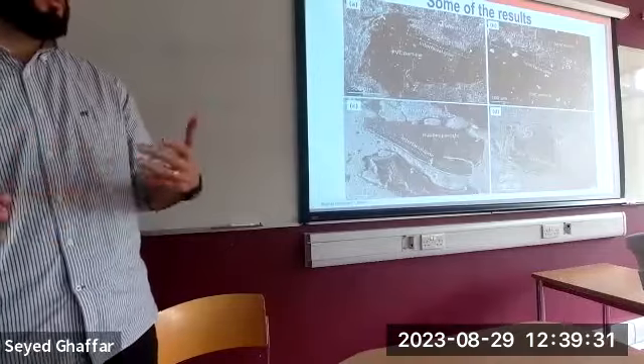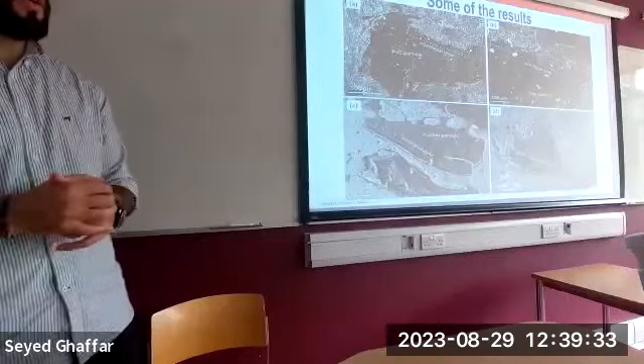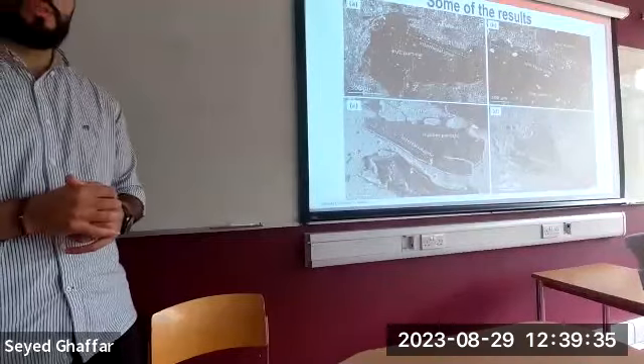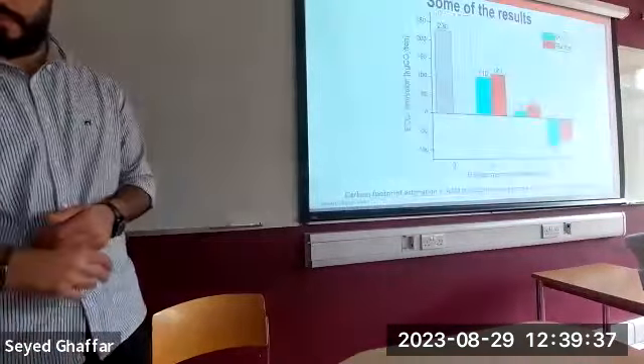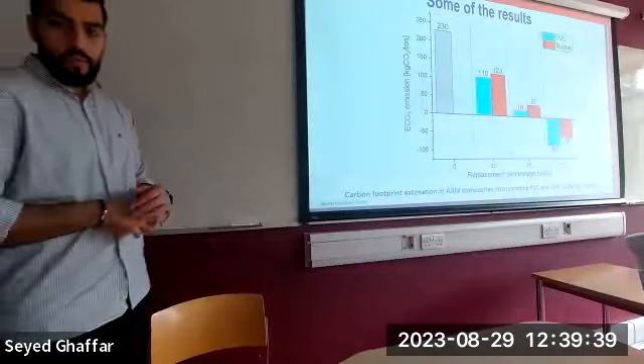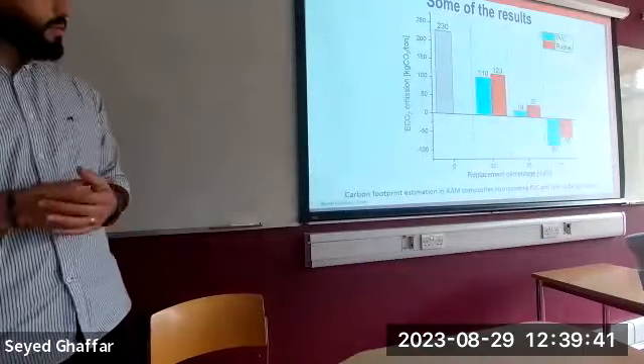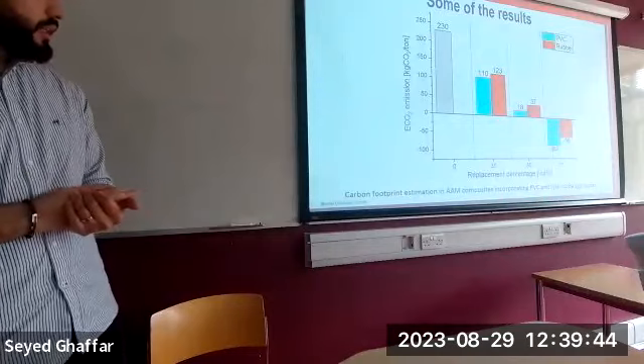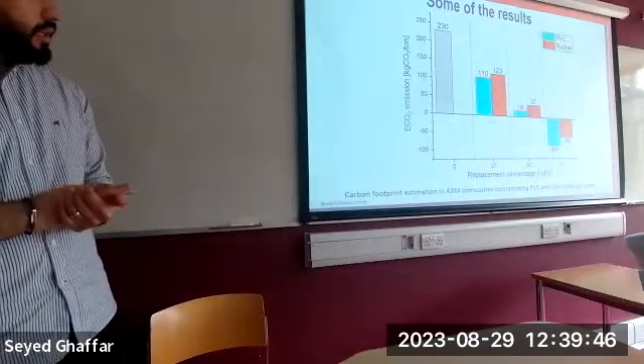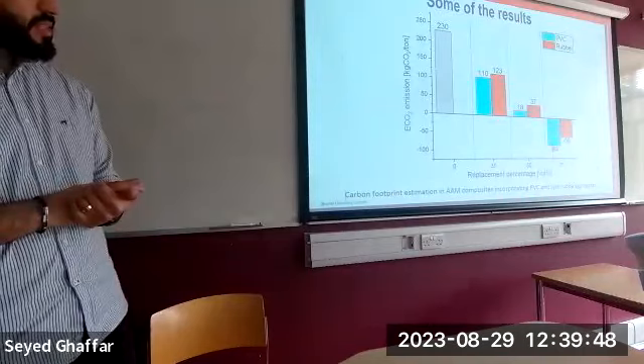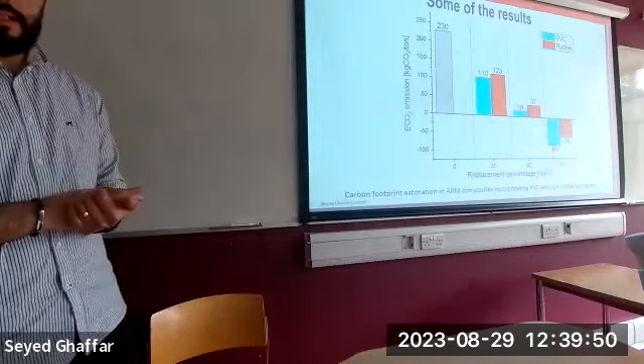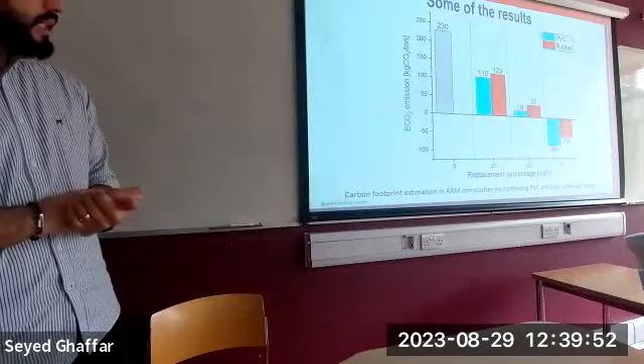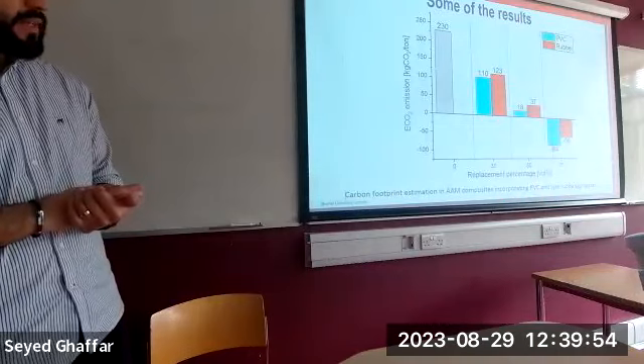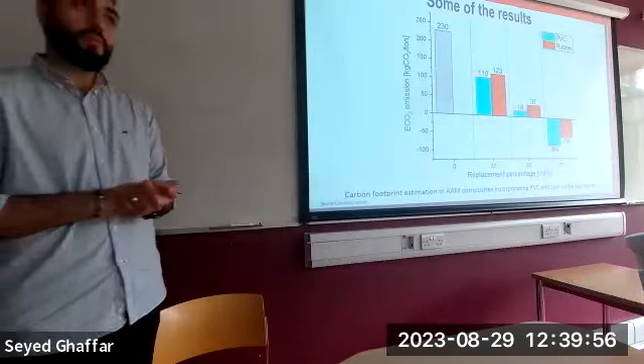Sound reduction, sound absorption, wall panels, which are used for highways, motorways to reduce the sound. Very important, we looked at the equivalent CO2 emissions, kg CO2 per ton of our developed materials using PVC and rubber aggregates. And the gray bar is looking at the control sample. So a sample which has been made from 100% sand.